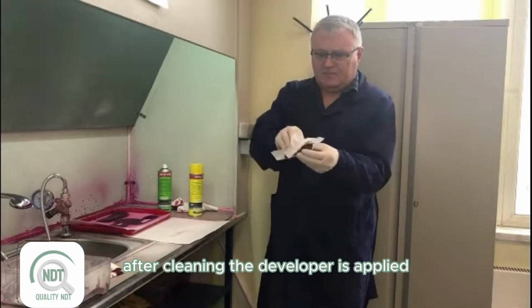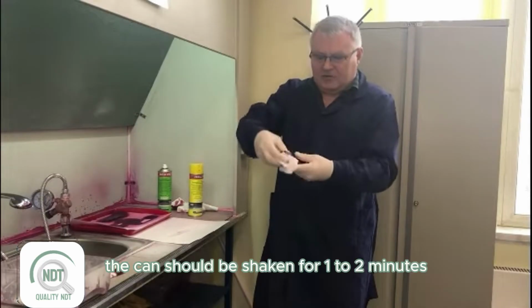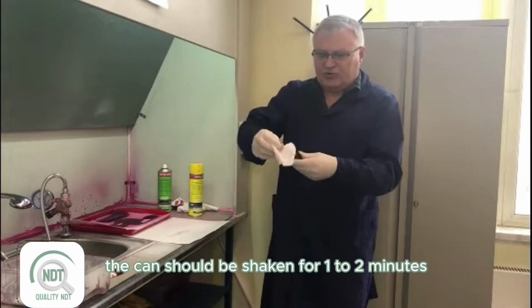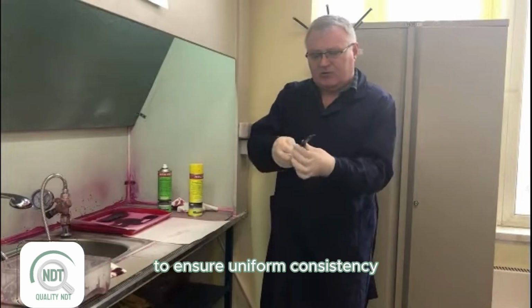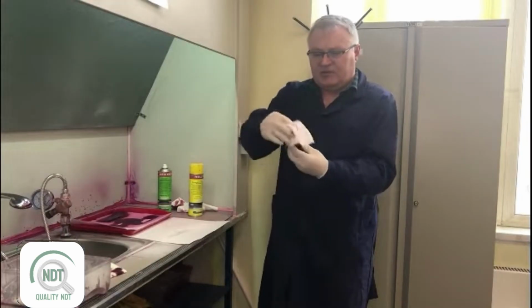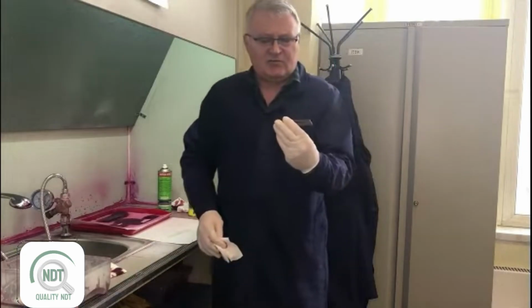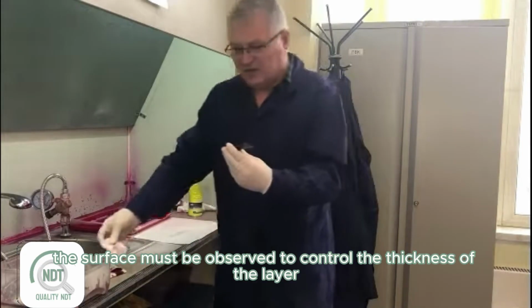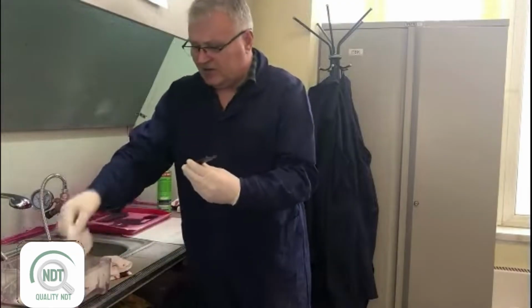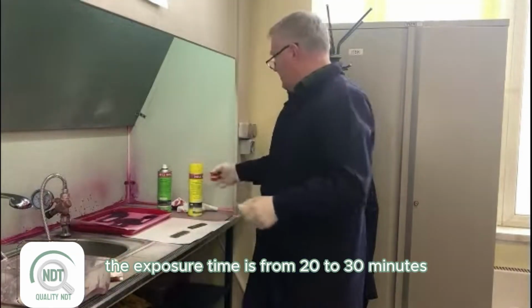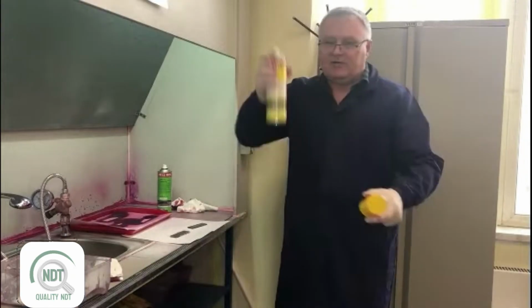After cleaning, the developer is applied. The can should be shaken for 1 to 2 minutes to ensure uniform consistency. While applying the developer, the surface must be observed to control the thickness of the layer. The exposure time is from 20 to 30 minutes.